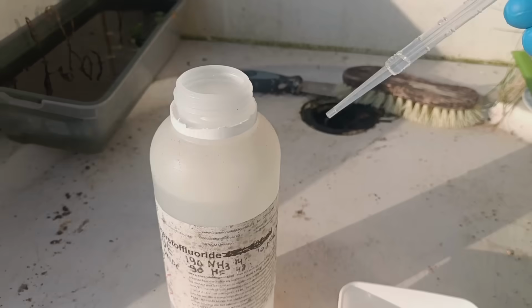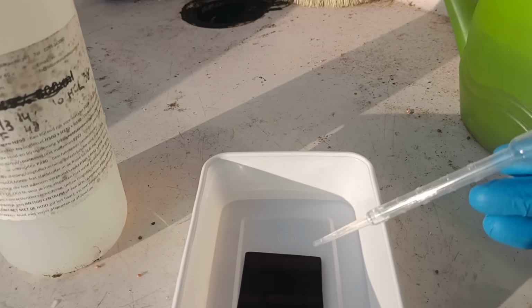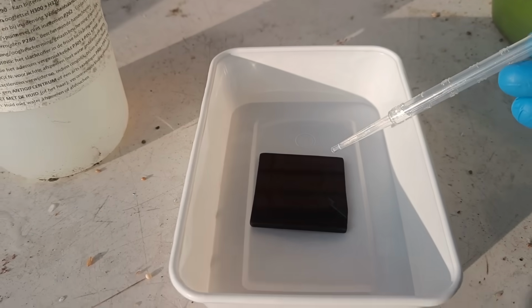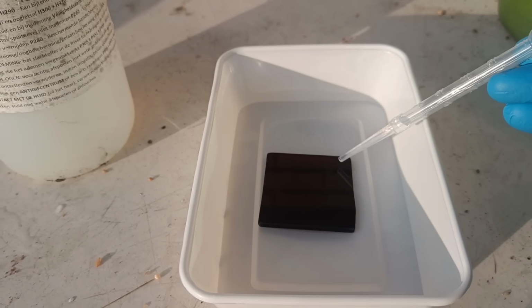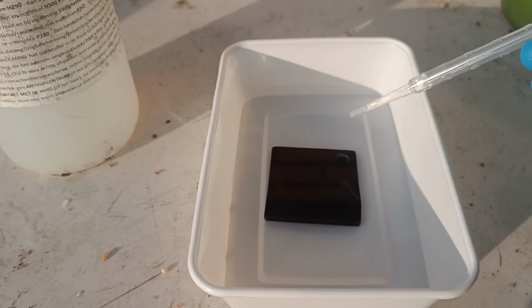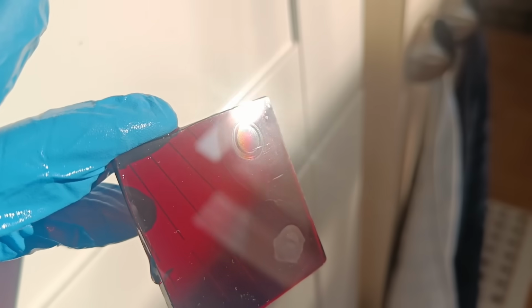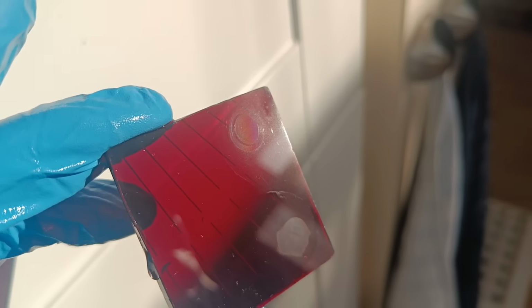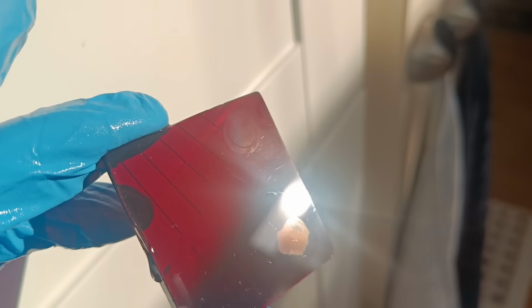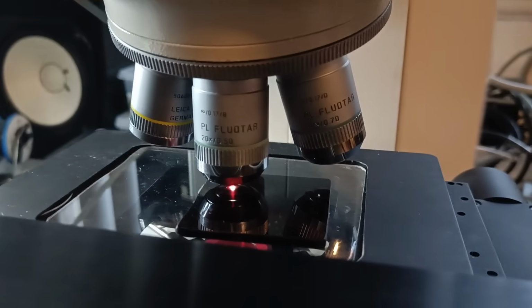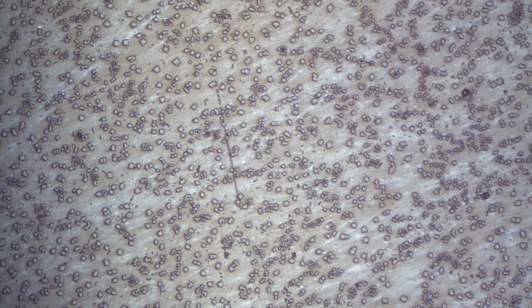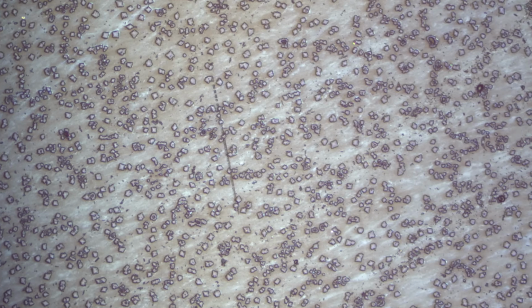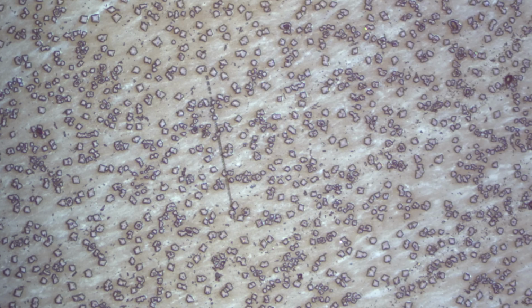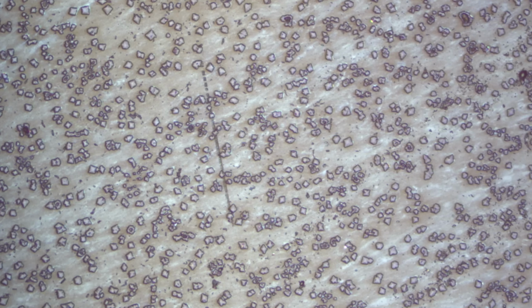Now let me quickly show you what the crystalline phase looks like. And for this I will mildly etch the surface of a piece of polished ceran using buffered oxide etch. After etching for about 1 minute, we see that the etchant attacked the surface, and when placed under a microscope we can clearly observe many small crystals in the etched areas. The size of the crystals is approximately, say, 4 to 7 microns, which is actually way larger than I expected them to be.